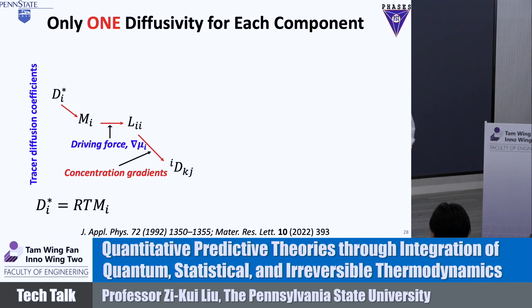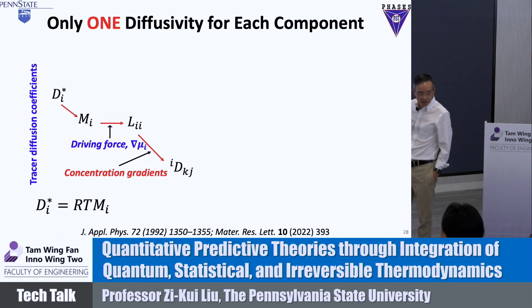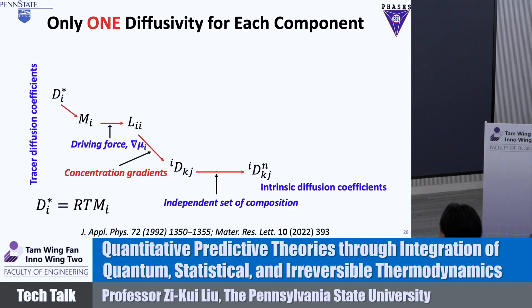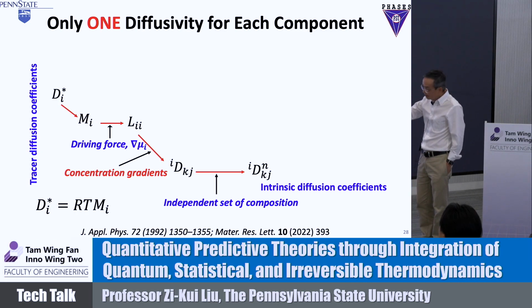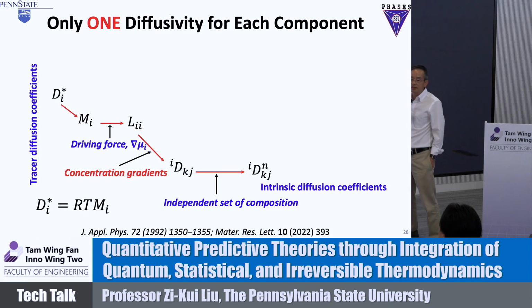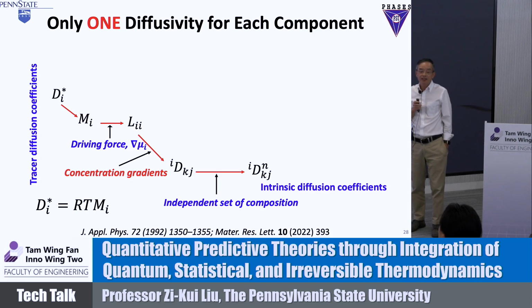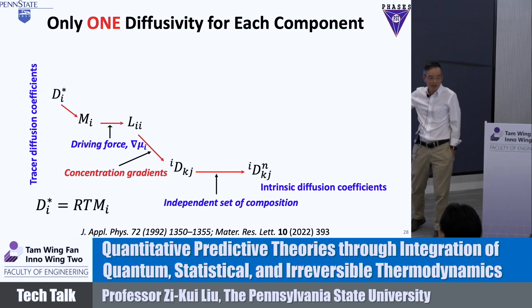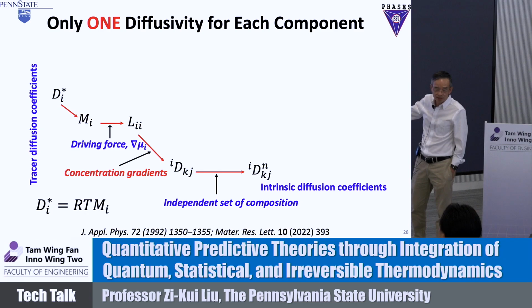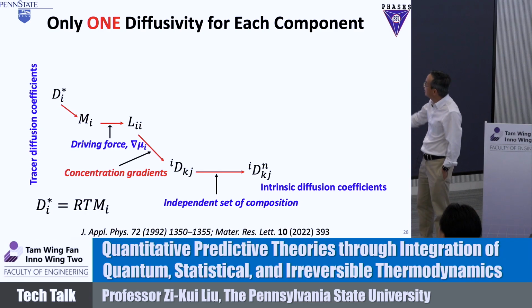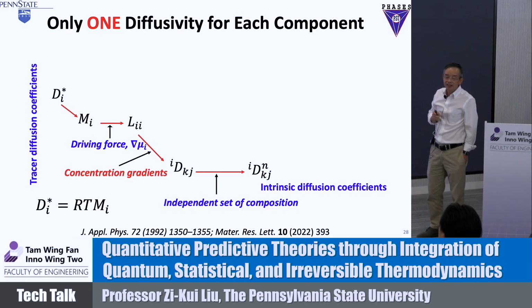If we change from chemical potential gradient to concentration gradient, we get a matrix now. How do we get that change? We'll talk about it later. Because in the concentration you have one dependent element, you can remove the dependent element, and you still have a matrix, right? That's the first transition. That's called intrinsic diffusivity. The intrinsic diffusivity is actually still the one diffusivity, but you get a matrix now. What does it mean? That means they are not independent. So what is the relation? Think about it; if you don't know, I'm going to show you in a minute. So that's one transition.